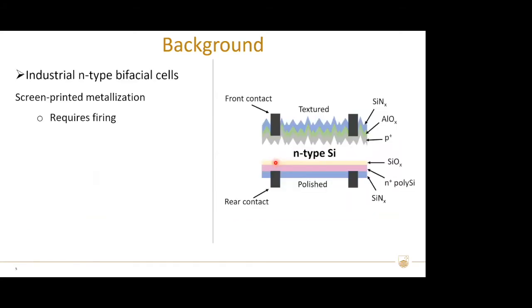For commercial solar cells with poly-silicon passivating contacts, an excellent solar cell efficiency of 25.53% has been reported by Jinko Solar on an n-type bifacial solar cell structure. The main fabrication process includes growth of thin oxide, deposition of intrinsic poly-silicon films, doping by phosphorus diffusion, creation of a P-plus layer, deposition of dielectric films, and screen-printing metallization followed by high-temperature firing.